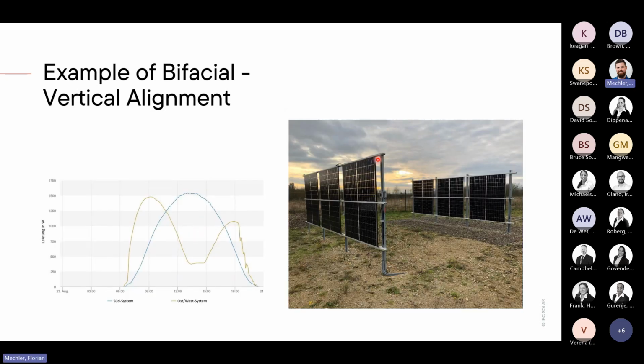Okay, then what we also tested is a vertical alignment. You see, the blue line is a test with the south direction, and this green line is an east-west system, like this here. And you see, the benefit of it is that you have 2 highest points. You have a higher point in the morning, and it goes down during the day, and it goes up in the evening. What is good about this? It's good because when you're working during the day, you have a higher peak in the morning where you take a coffee or a shower or what else, I don't know. And in the evening, when you do have any